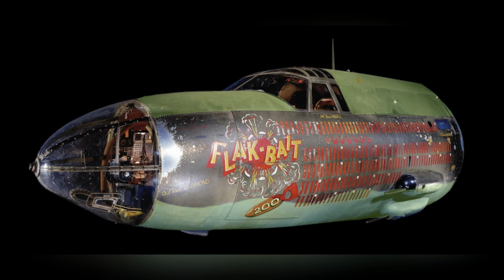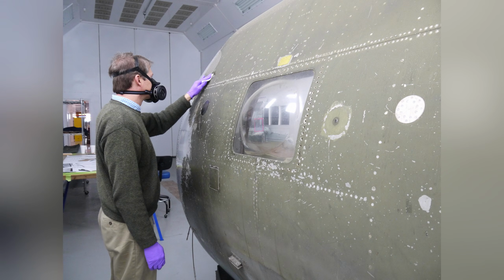Modern conservators now treat the 1976 display preparation as a later intervention that must be physically unwound. The goal is to remove the aesthetic additions without damaging the authentic World War II surface beneath them. The decision to remove the 1970s overpaint is constrained by the fragility of the layers beneath it. The later paint sits directly over original olive drab paint, zinc chromate scab patches, graphite signatures, soiling, and abrasion marks left by wartime use. Before any removal can begin, conservators must establish the layer structure, thickness, solubility, and hidden visual evidence through testing rather than assumption. It has to be tested, mapped, and approached in controlled stages.